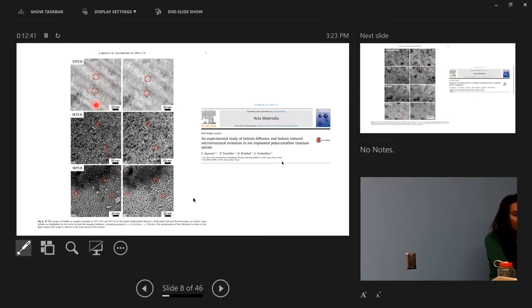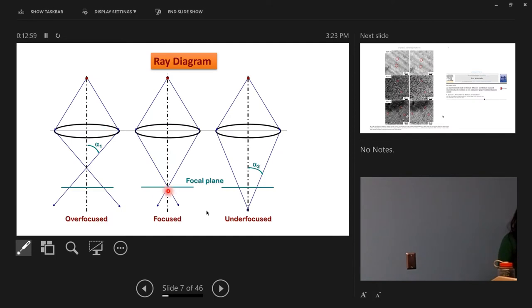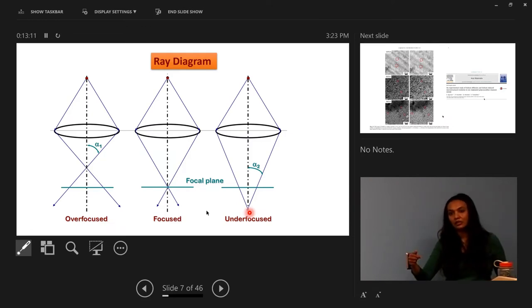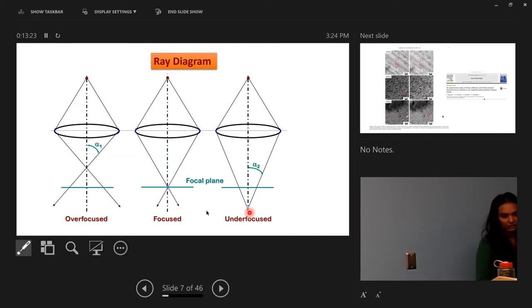I mention Celsius because all the furnaces that we use in our labs are in Celsius. What we see is the formation of bubbles. The best way to characterize it is to take them to the microscope and start changing the focus. That means you are bringing your condition from focus to over focus to under focus. How do you change the focus of any lens? In an electron microscope, by simply changing the current. In an optical microscope, you change the distance manually. Here you cannot do that, but you can play with the current conditions.